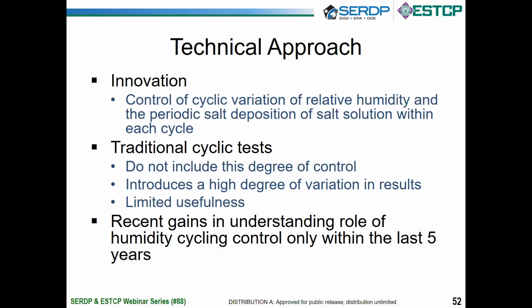So the innovative technical approach for this is that we're relying on the cyclic variation, which is informed both by previous research as well as data collected from the operational environment. Cyclic variation of relative humidity, as well as the salt deposition of specified salt solutions. As I mentioned before, traditional cyclic tests cannot provide this degree of control for relative humidity, and we've been able to see a large amount of variation in results from these tests as well. A lot of this understanding has been gained within the last 5 or 6 years, and so we feel we are on the forefront in terms of developing this technology.